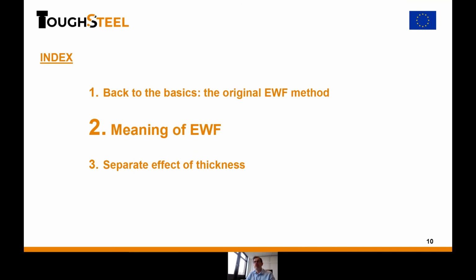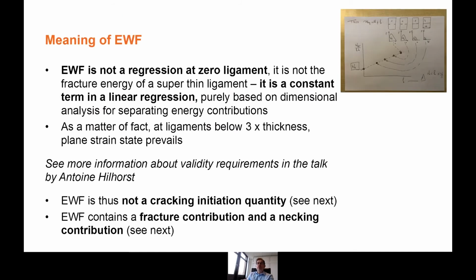Anyway, that was already covered before; I just rephrase it for some aspects in my own work. The meaning of the essential work of fracture: an error that is often made when explaining it is to consider it as a regression at zero ligament. Somehow this would be the work per unit area you would get if you could take a very, very small ligament. That's not correct. It's not an extrapolation at zero ligament. The essential work of fracture is the constant term in a linear regression.